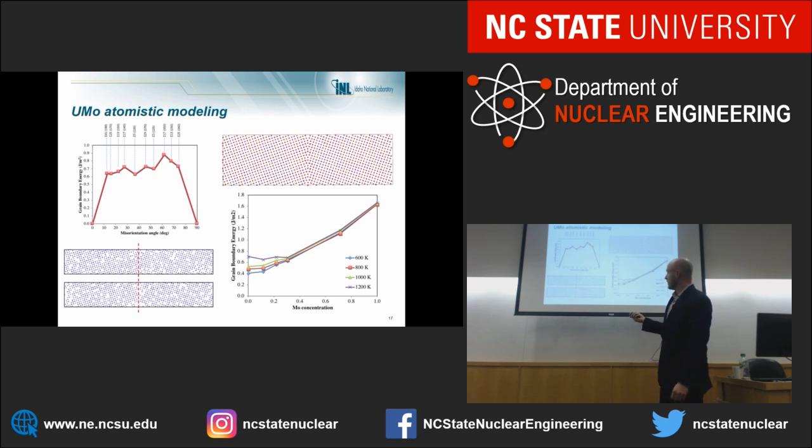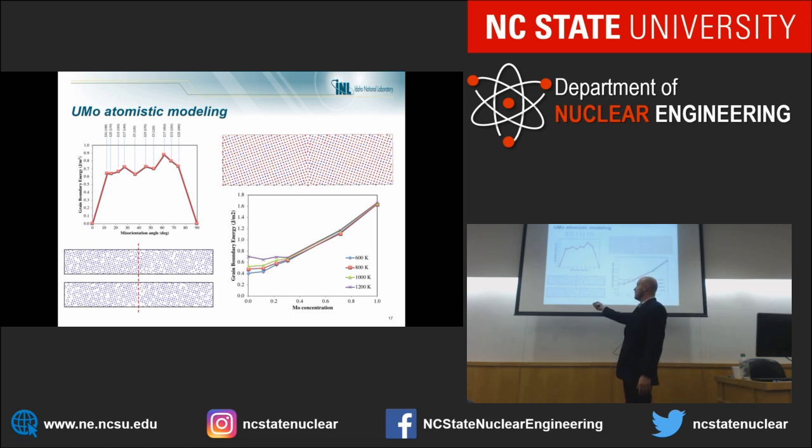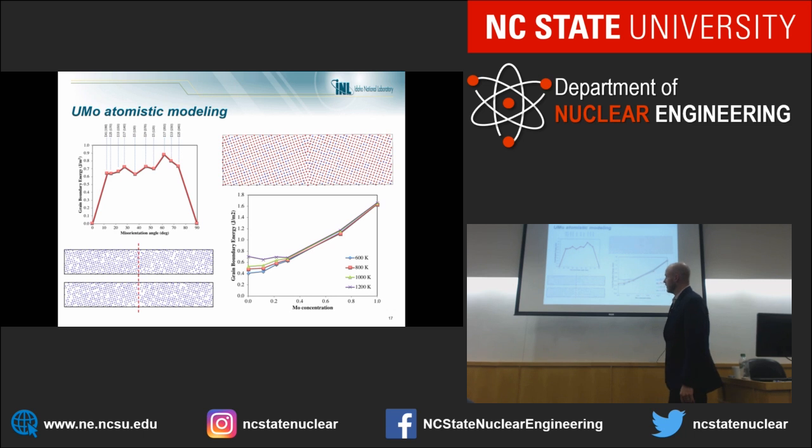So we're speeding up what's going to happen eventually, but we're kind of cheating on our way to make that happen. And the thing that we saw, so I'm showing only moly atoms here. I've deleted all the U atoms just to be able to see it better. And so I have grain boundaries on the interior and on the edges of the system. We have fewer moly atoms that actually exist in the grain boundary region. So we're seeing actively depletion of moly along these grain boundaries within these systems. So all of this makes sense, and it explains why we're getting decomposition in our fuels as well.